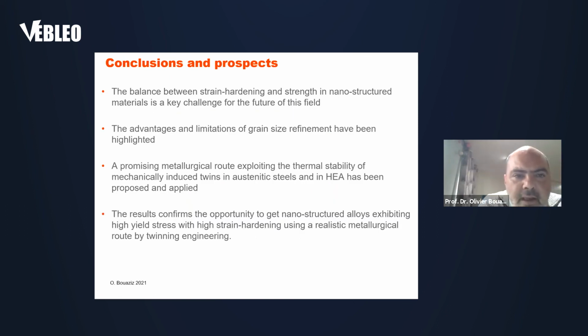So in conclusion, the balance between strain hardening and strength in nanostructured material is a key challenge for the future of this field. The advantages and limitations of grain size refinement have been highlighted. A promising metallurgical route exploiting the thermal stability of mechanically induced twins in austenitic steel and in high entropy alloys has been proposed and applied, and the result confirms the opportunity to get nanostructured alloy exhibiting high YS with a high strain hardening using a realistic metallurgical route by twinning engineering.